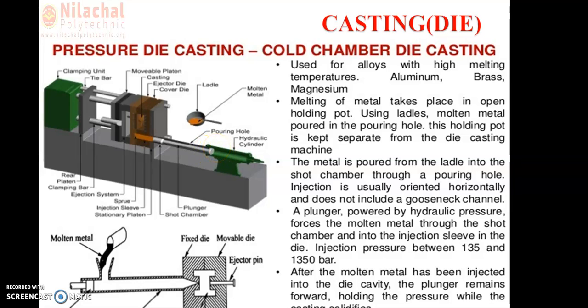High pressure tends to increase the fluidity of the molten metal possessing relatively low temperature. Lower temperature of molten metal accompanied with higher injection pressure will produce castings of dense structure, tending toward dimensional accuracy and free from blow holes.